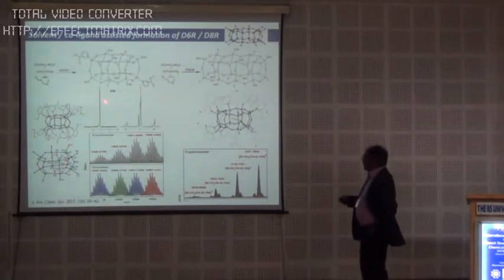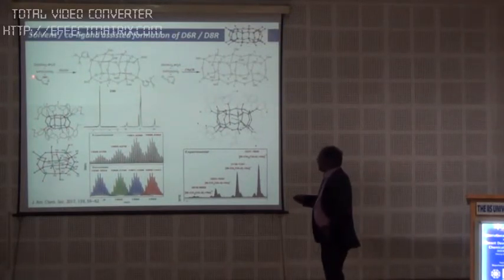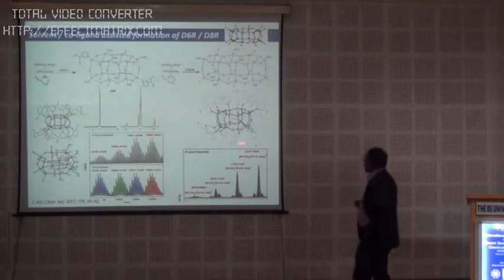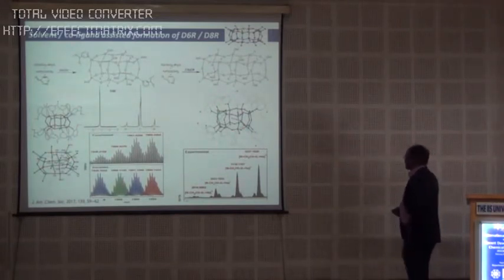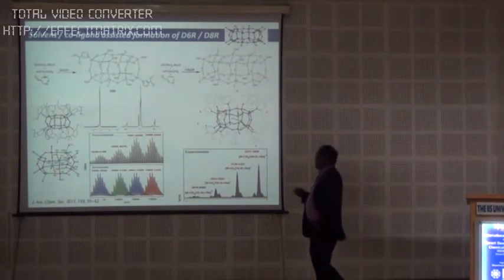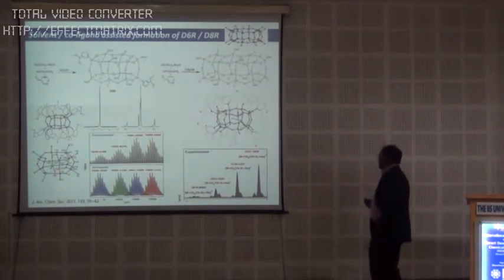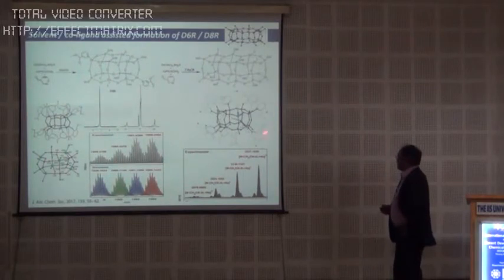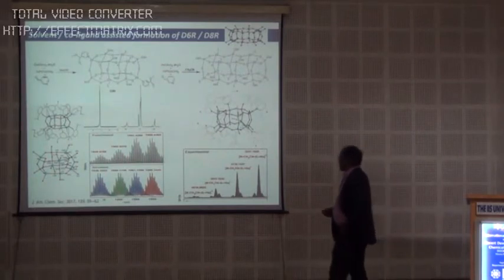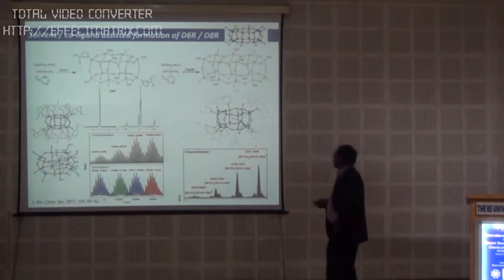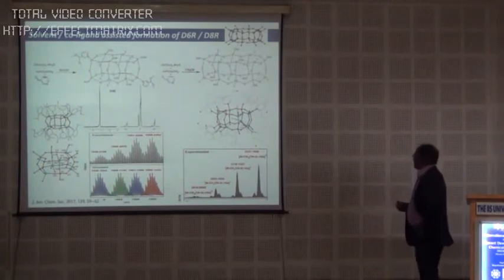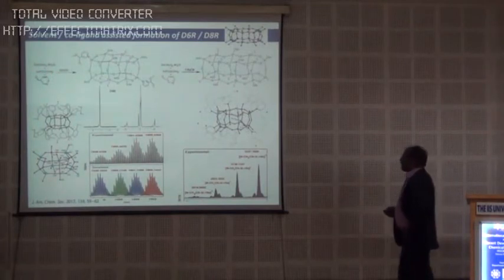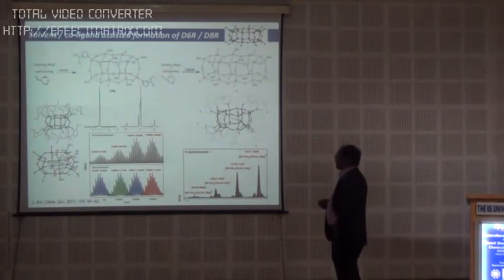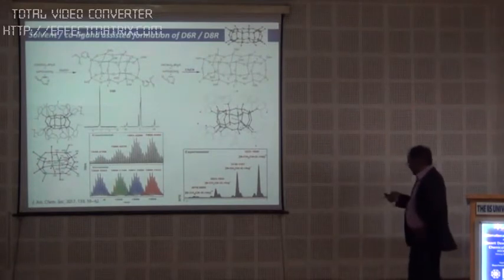And we are even fortunate to have 6 formyl groups, because these are formyl pyridines, and 8 formyl groups here. That means straight away we are in business to make the cage-like molecules or molecule-like cages by using the imine methodology. If luck would have it, you can use the other 6 or other 8 centers, and you can have these bigger structures come. But I think that kind of summarizes our efforts on building porous solids using a simple phosphate monoester, namely the diisopropyl phenyl ester of phosphoric acid, and using a variety of metal salts.